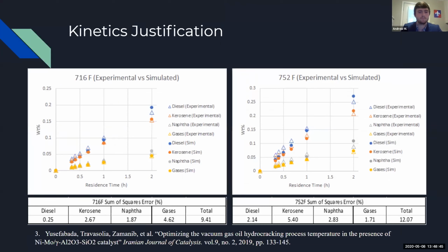So our kinetics article had 6 different temperatures, and we plotted the weight percent versus residence time, and we changed what the weight percent residence time was by changing the frequency factors and activation energies in the Arrhenius equation. And as you can see for these bottom 2 temperatures, the 716 and 752, they fit pretty well. And then for 716, we got about a 10% sum of squares error. And then for 752, we got about 12%.